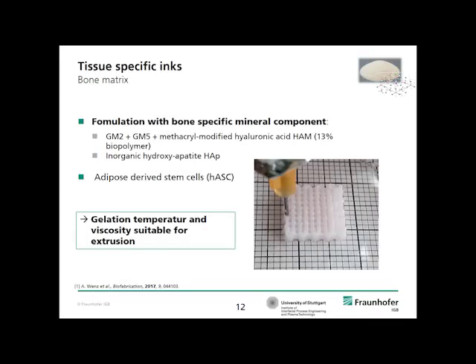So we do not print the ready-made tissue, but we print cells that should then be able to reproduce the tissue by themselves. In this case, we formulated the ink such that we can use an extrusion-based technology, and we adjusted the gelation temperature of the ink and the viscosity such that we achieve these self-supporting filaments, so that we can print layer over layer without the material melting on the substrate.